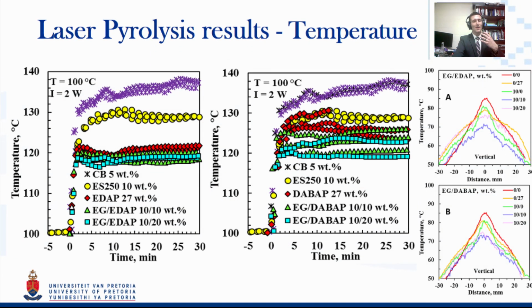Here on the next slide shows an indication of, on the right, what the infrared camera itself actually picked up, and that is that here one can see that the overall temperature profile is much, much lower for especially the binary systems with EDAP and expandable graphite. In fact, it once again seems to indicate that there is a synergism of sorts in that it is lower than any of the individual materials are able, or any of our expected results if one quantified the results together.